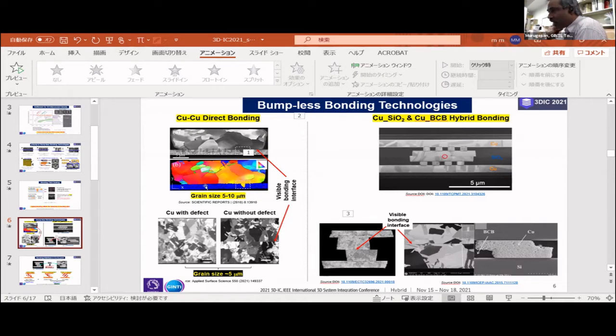None of the copper orientation matches with your bottom one, so there's no copper diffusion at all. You may say that you got very good copper bonding, but I would say there is no copper diffusion between your differently oriented grains. It clearly shows here. Even though you got very nice copper bonding and a bonding strength of 10 megapascal or 25 megapascal, in my view your copper grains between top and bottom are always disconnected. Obviously you may get some electrical connection, but from an atomic view, there is no copper grain diffusion between either 110 or 111 plane.